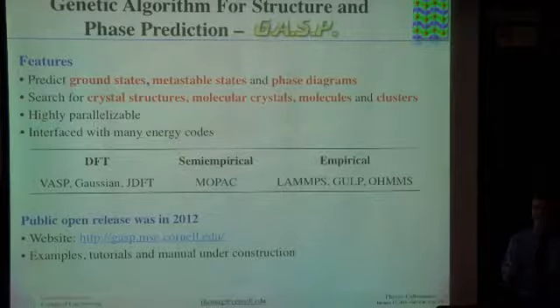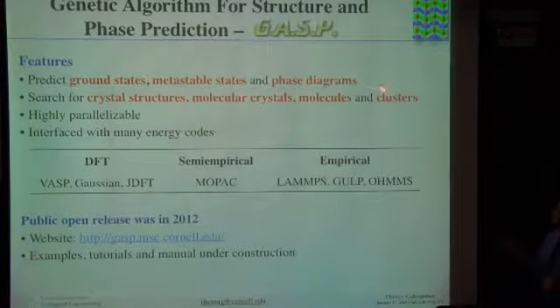It turns out that the sulfur, unfortunately, doesn't stay in the electrode. It dissolves in the electrolyte, forming these little lithium clusters, and deposits somewhere else in the battery. The battery only lasts one round. You can't recharge it. And so we're interested in figuring out what those clusters are, what's happening there. That's why we're looking at these lithium-sulfur clusters, also with our code.